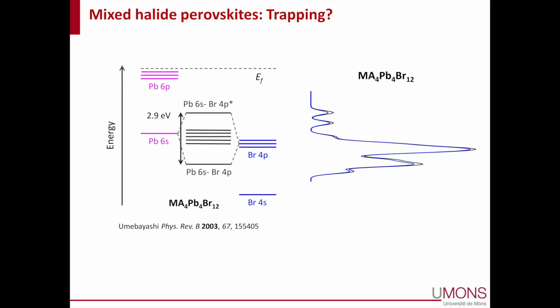But we were a bit surprised by those results because we thought that, okay, you start with a lead bromide, say, a pure compound, and this is a typical situation for the valence band of those materials. So you have strong hybridization between the lead 6s and the bromine 4p orbitals, giving rise to the valence band edge, which is this anti-bonding combination.